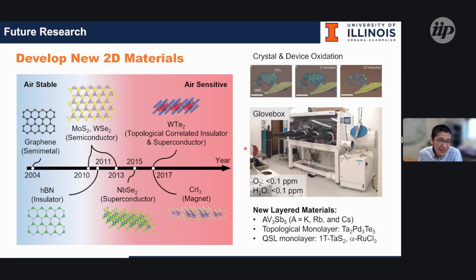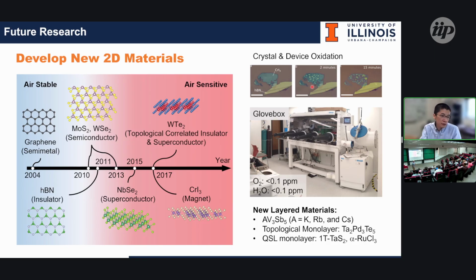Yeah, exactly. The hardest thing is, as you can see here in the crystal, for example in chromium triiodide, even after 2 minutes the sample will get oxidized. And if you cover it with hBN with the chromium triiodide, you're still getting oxidation very easily in 2 minutes. For tungsten ditelluride it's a very similar case — if you cover it with hBN and then try to transfer from the glove box to your measurement system, you need to really hurry up. Especially for STM study, people need to bake and apply high temperature to the sample, so it's extremely hard to explore such a system.